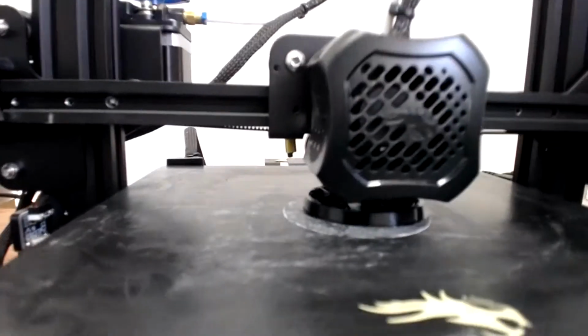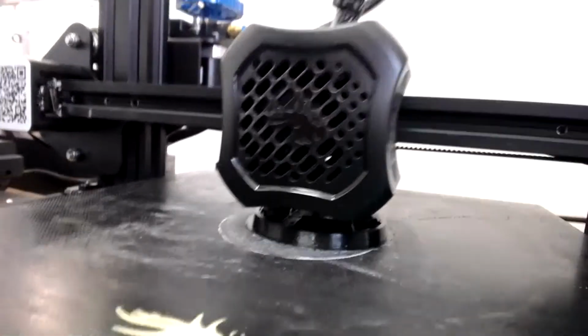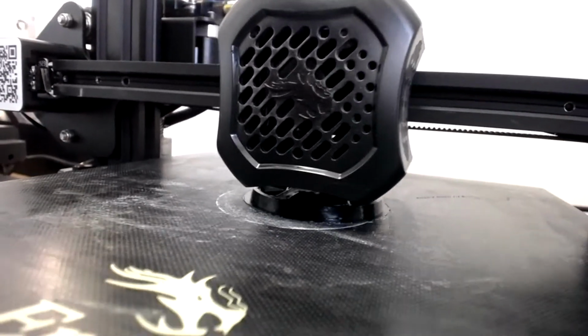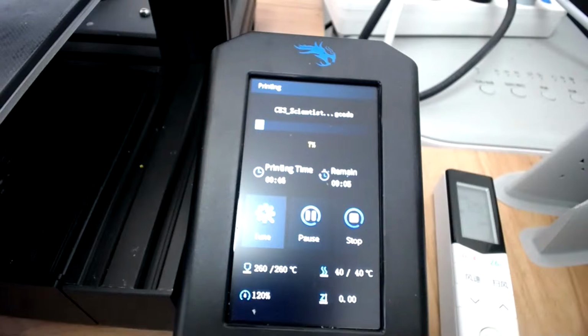This printer is the one that is printing the material scientist. You can see here, it looks like it's going to be pretty successful. We have very good and consistent layers, but let's see how it goes. I'm printing this at 260 degrees, which is not recommended on the Ender 3, because if you print at 260 for too long, I think it's going to damage the print head pretty quickly, but that's just for testing purposes. I'm pretty sure most of you have modified yours with an all-metal hot end. Otherwise, you could print at 250. You will have slightly lower layer adhesion, which is still not bad if it's very dry, but 260 is more recommended.